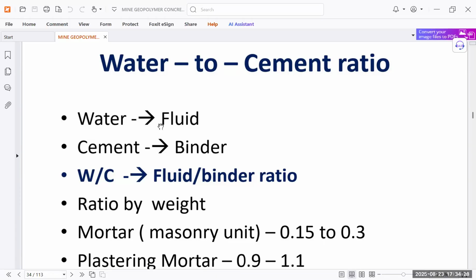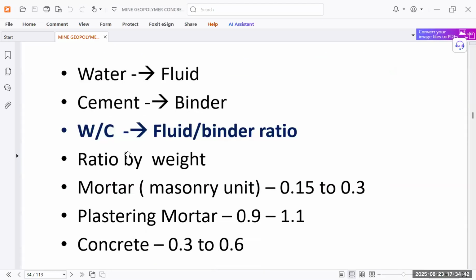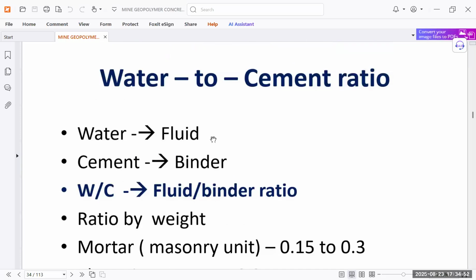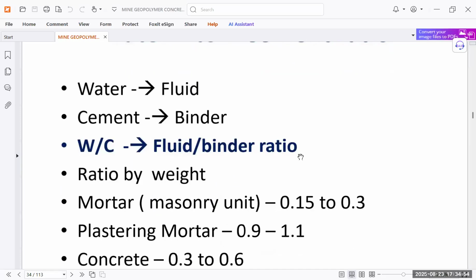Here the water cement ratio will not be there, because neither are we using water as pure water, nor are we using cement. So it will not be the water cement ratio, it will be the fluid binder ratio in this case. And the ratio by weight will be 0.15 to 0.3 for mortar masonry, 0.9 to 1.1 for plastering mortar, and 0.3 to 0.6 for concrete. So this is the change which we have made in geopolymer concrete: the water to cement ratio has been changed to the fluid to binder ratio.